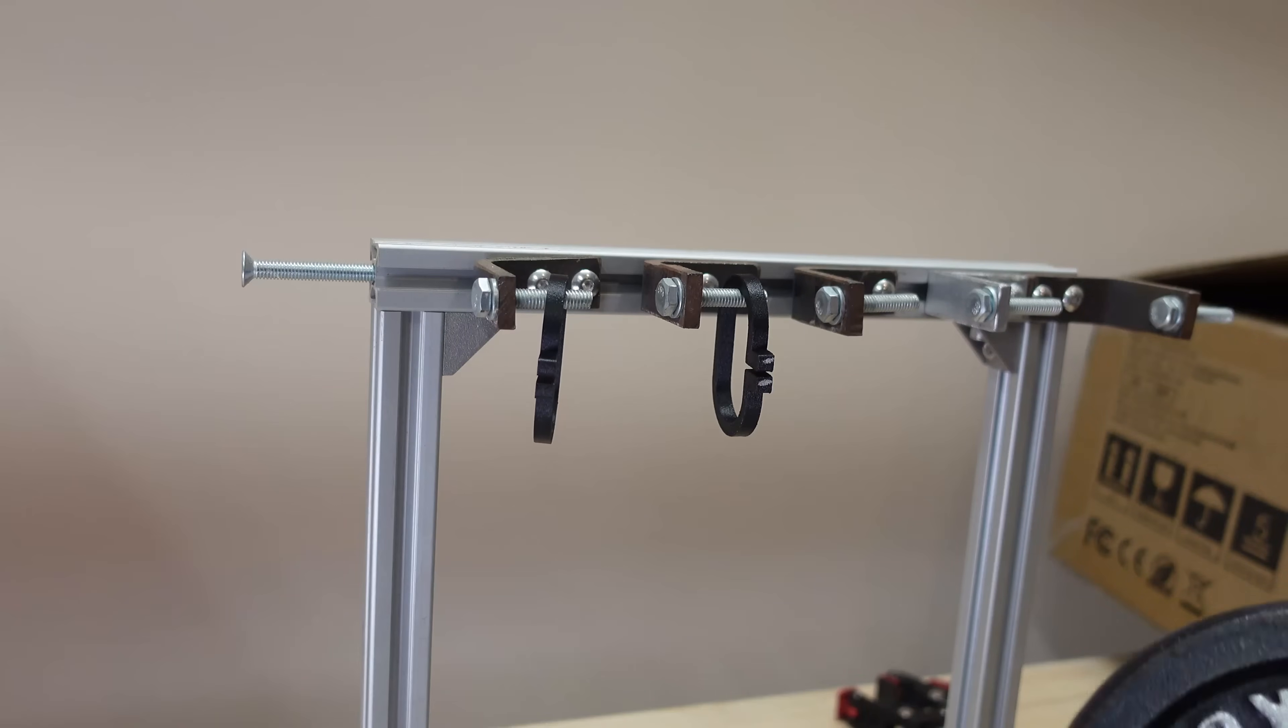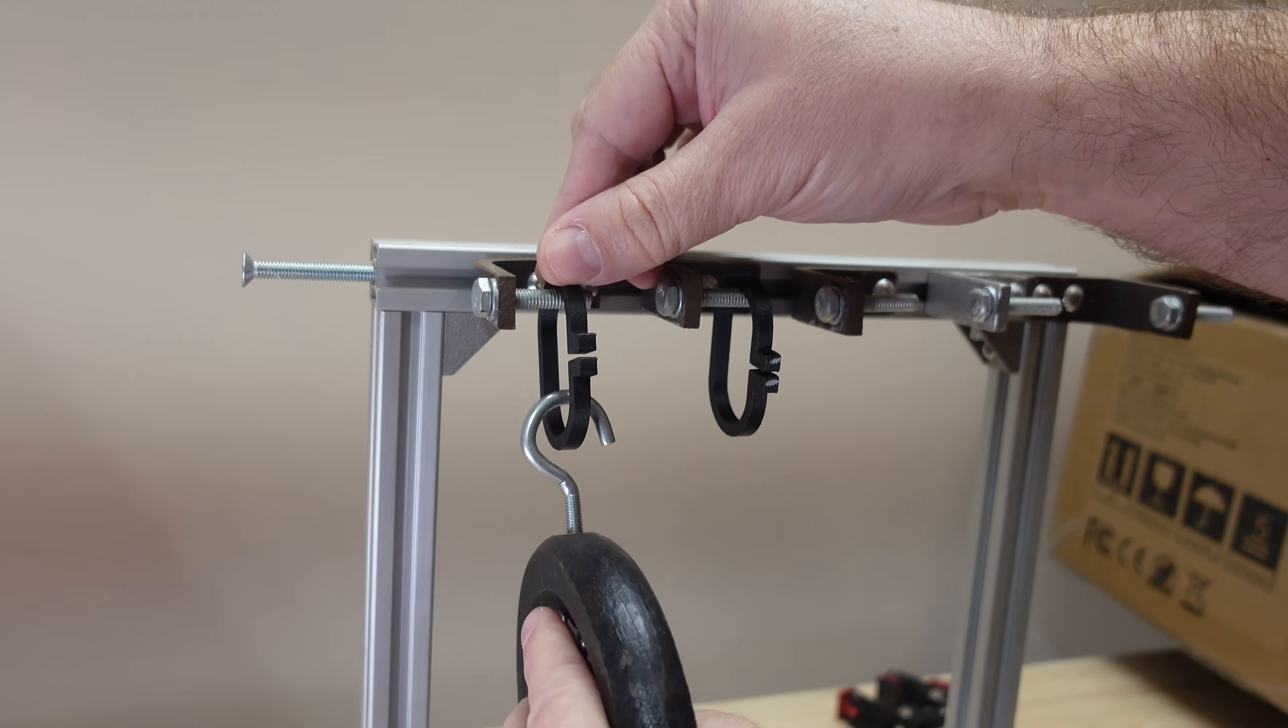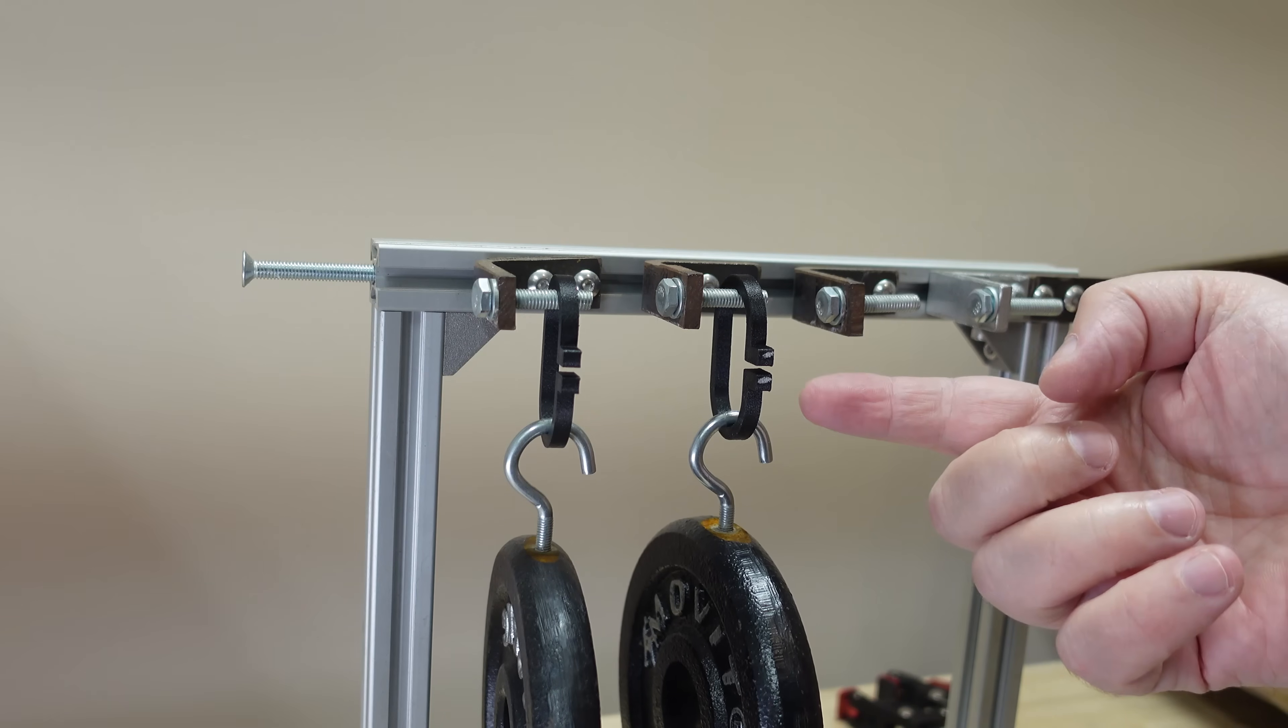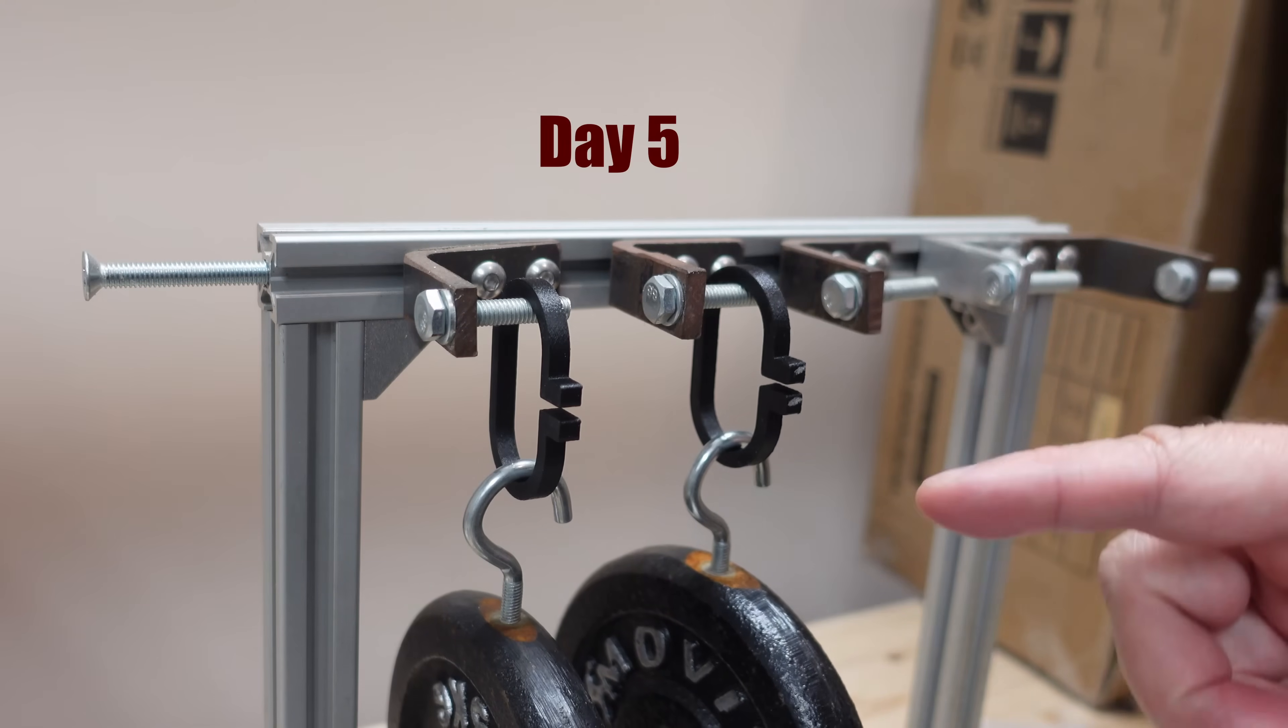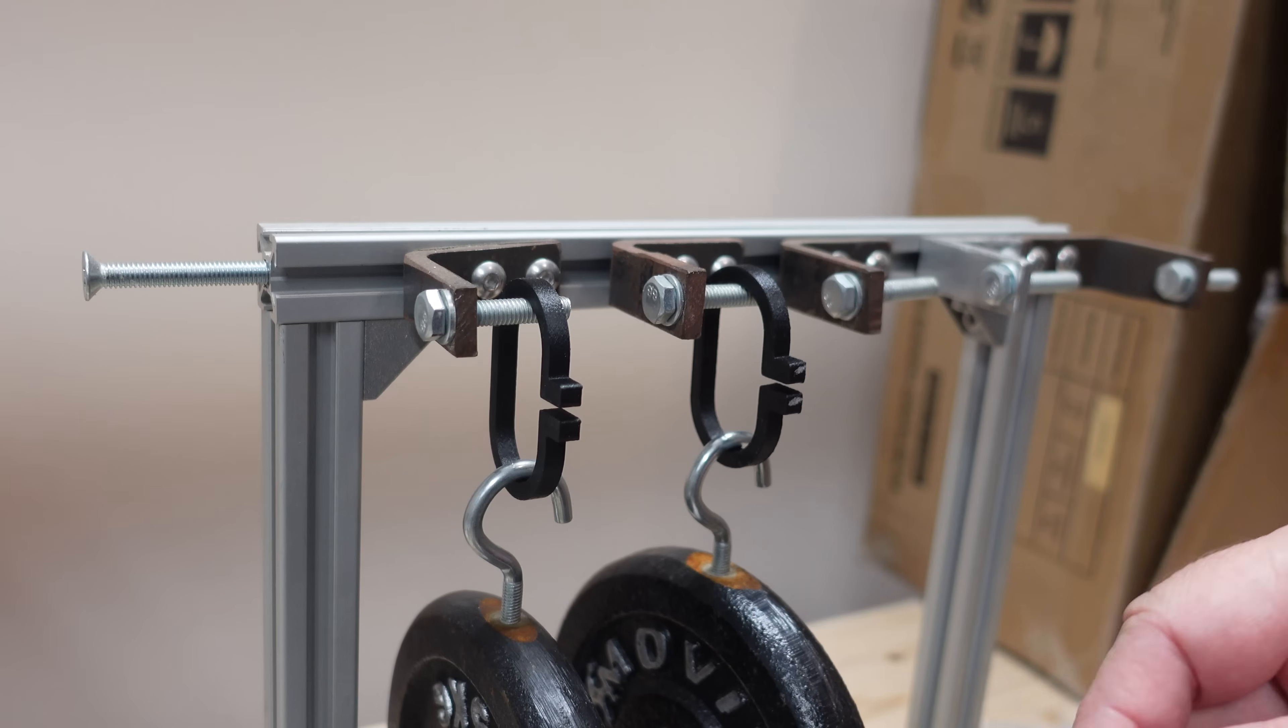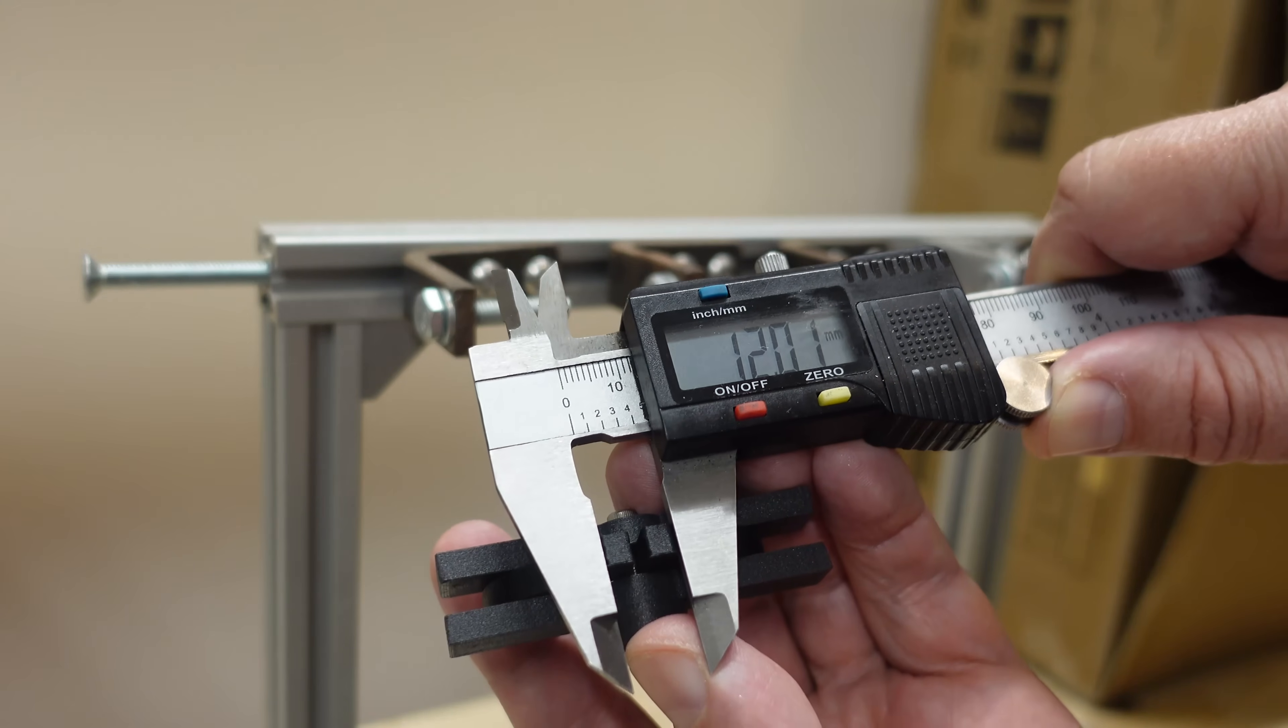The creep test, the deformation under the constant load of 1.25 kg and I will do parallel this test. This is the PPACF nylon and this is PETCF. And now we measure the distance between two reference surfaces. This is a good sign, even after one day visually I cannot see any additional deformation on them. I already measured them and the additional deformation of the PPA compared to the day is zero. This means initial deformation is only 0.1 mm. Now let's remove the load. There is not even measurable parameter deformation on this test object.